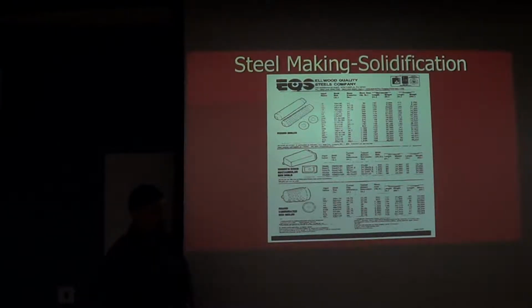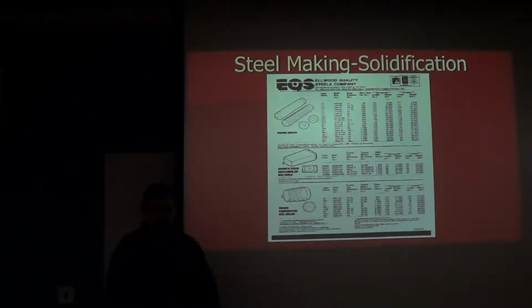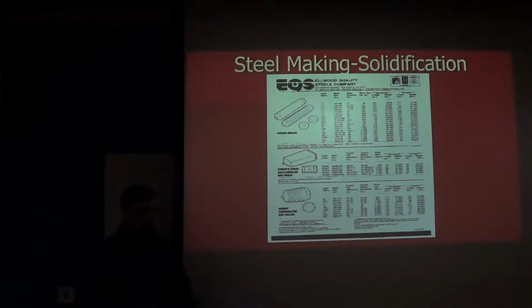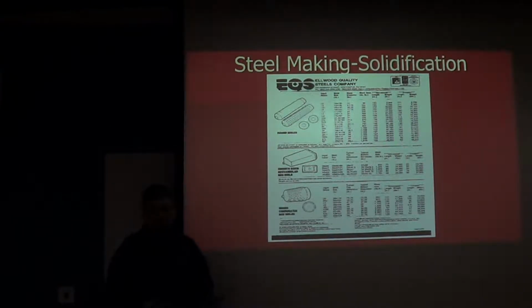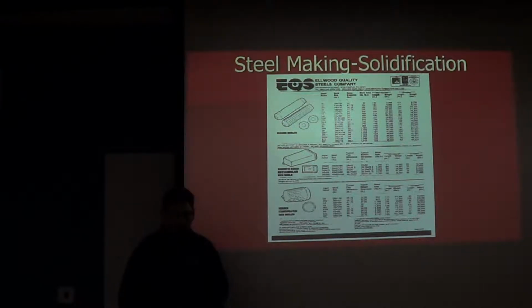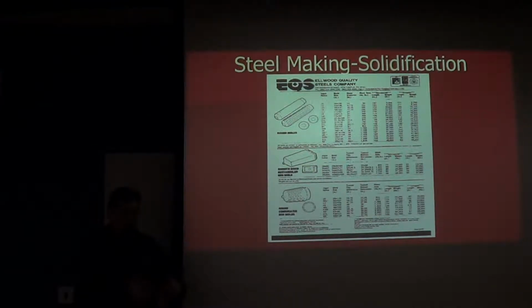Typically, a customer would say, I need you to do an ultrasonic test on this, and I want it to meet something like, say, a 5/64 flat bottom hole, or a 1/16 of an inch flat bottom hole. The smaller that criteria, the cleaner we have to have the steel, and that drives what ingot configuration we're going to pick for their product.